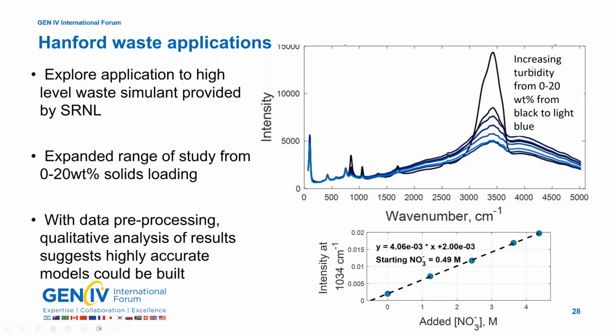Using that close focus probe, this shows an example of some of our variable turbidity measurements, where we have from 0% added solids to 20 weight percent added solids. In this series of spectra, the black line is 0% solids where there are no solids in solution, all the way to the bottom spectrum here, which is 20 weight percent solids. You can see that the signals are attenuated as we go to higher and higher weight percent solids. They're attenuated, but they do not go to zero. So we're able to get information from these spectra even at 20 weight percent solids.